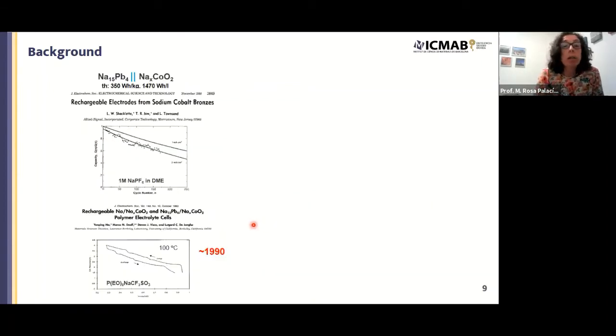So this technological concept is not new. It comes from the early days of intercalation chemistry, where intercalation of many ions in inorganic structures was studied, such as lithium, sodium, and many others. And even some first proofs of concept were given in the early 90s, but then the field was abandoned due to the advent of the lithium-ion technology, so everybody focused on that technology. But here you can see some results of a full cell using a sodium-lead alloy as negative electrode and sodium cobalt oxide as the positive electrode, and using either liquid electrolyte, sodium PF6, as you can see, or even a polymer electrolyte working at 100 degrees.